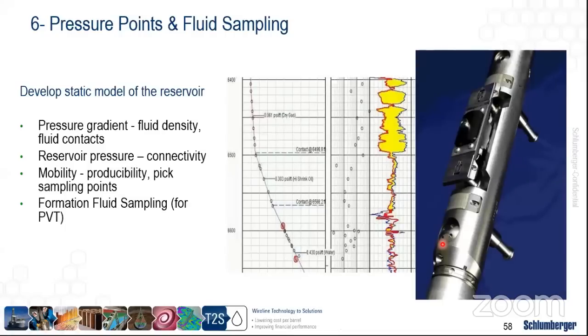In this case, in order to acquire a pressure point in sampling, we need to lower a pressure sampling tool, which is typically a tool that has a vacuum inside, and then it has a probe, what we call an inlet probe, that can allow fluid to go inside the formation. And then once we create a drawdown, which is a negative pressure, then we can identify and measure the reservoir pressure itself inside the formation. So this is very important when we start to appraise a well in order to understand the expected reservoir pressure.